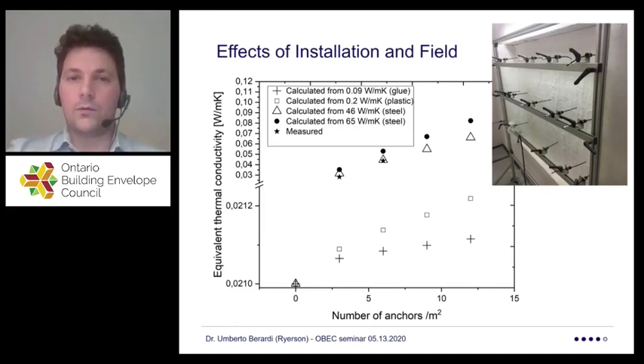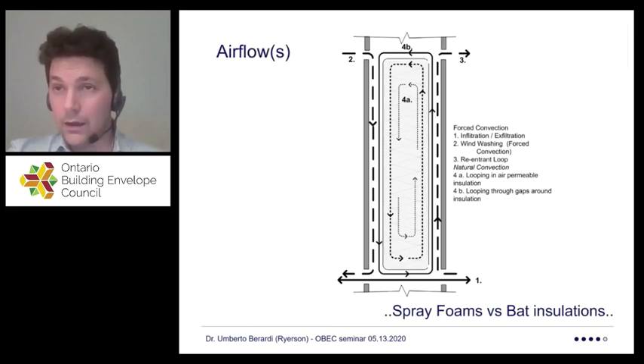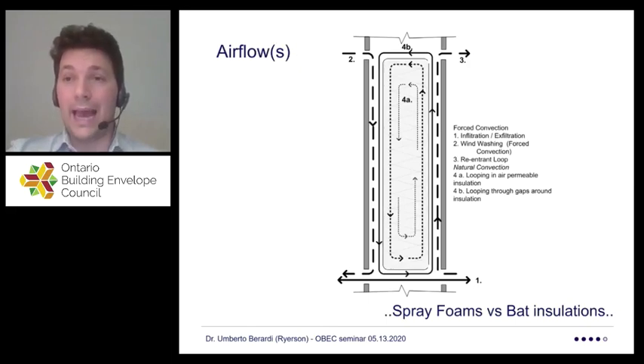And on the x-axis of this graph, you see the number of anchors per square meter. So if you remember the two photos of Toronto downtown buildings, they were typically in the range of over 10 fastenings for a single square meter, okay? That means that the equivalent thermal conductivity in the field becomes completely different from the theoretical technical sheet. So somebody could say, okay, Umberto is suggesting we not put a lot of fastenings. That's not necessarily the truth, because as soon as you don't put fastenings, what you start having is a lot of airflow around the insulation. Airflow at the edge of the insulation, but also airflow within the insulation. More airflow means more conduction. More conduction means more effective thermal conductivity.